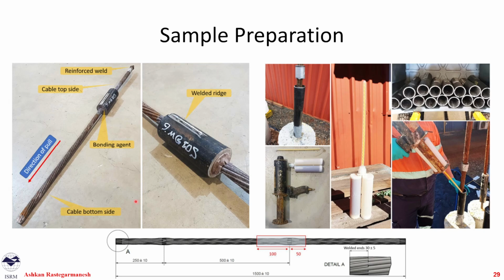For sample preparation, on the left we see the sample. So this was our anchor tube length. After the preliminary test, we realized that a 300 millimeter anchor tube was too long and it would break the cable. It gets very high, up to the yield strength of the cable. So we went for 150. We had the same anti-rotation weld on it, and we put some extra reinforcing welds on the top.